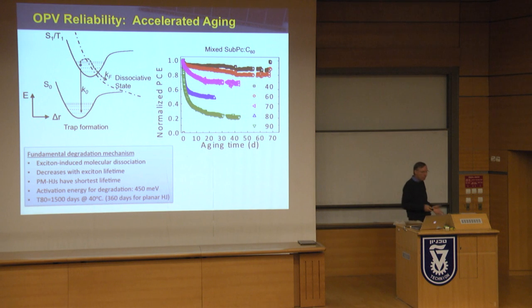Now, contrary to OLEDs, with OLEDs, the higher efficiency, the longer the lifetime, because that means to get a certain brightness, you don't have to drive them very hard. But with the PV cell, the higher the efficiency, the shorter the lifetime, because the current is higher. So it goes exactly in the wrong direction. This just shows one of our cells, and you can see this is the power conversion efficiency over a period of 70 days of continuous illumination.